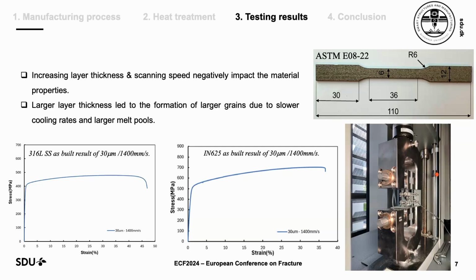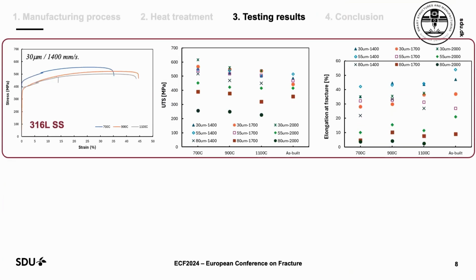As we see here, these are the stress-strain curves only for these two alloys for as-built. We followed the standard ASTM E8 to do simple tensile testing. We used a universal tensile test machine and an extensometer to obtain accurate strain. And for heat treated, this is just an example of a stress-strain curve.